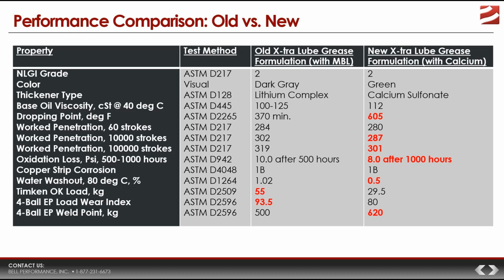Wherever you're using grease, it needs to maintain its consistency under high shear conditions over as long a period of time as possible. So they use the ASTM D217 test to document how the grease's thickness may change over time.